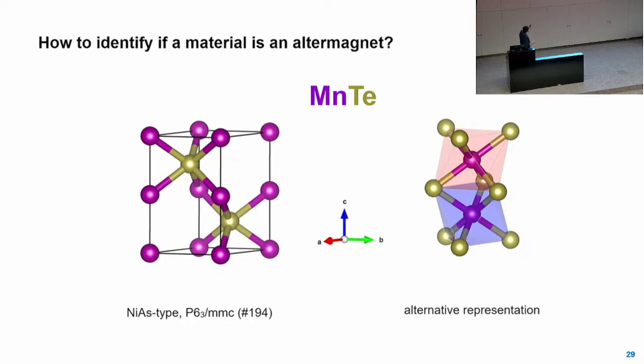So manganese telluride has this kind of crystal structure. It's called nickel arsenide type crystal structure. It's a hexagonal structure. But for the purpose of today, I just draw it in a different way. It's an equivalent representation. I put the manganese atoms, these purple ones, into the center of octahedra of the tellurium atoms. And you see I already indicate there's one blue octahedron and one red one, because they will have the opposite spin polarization.